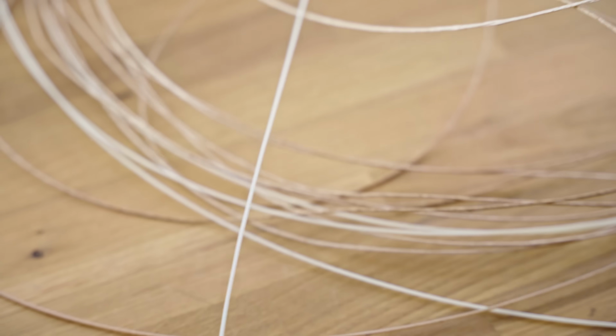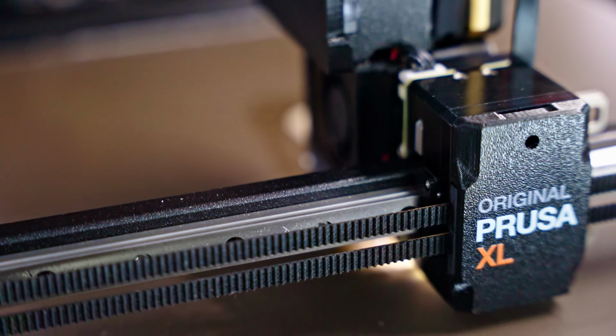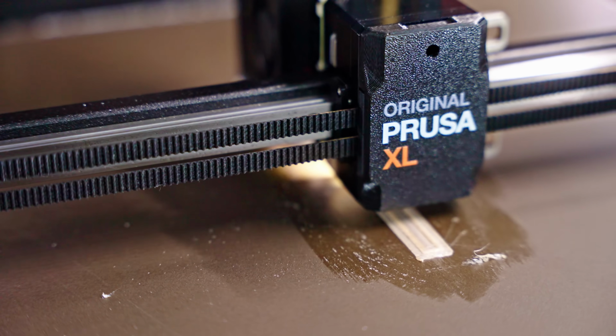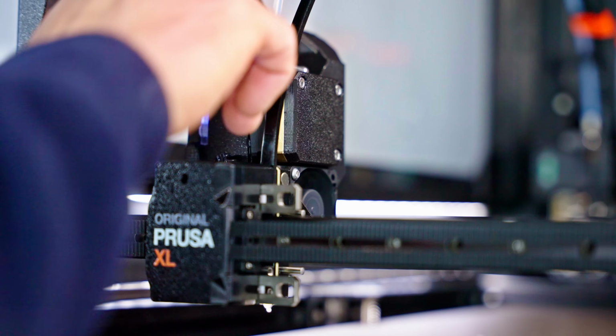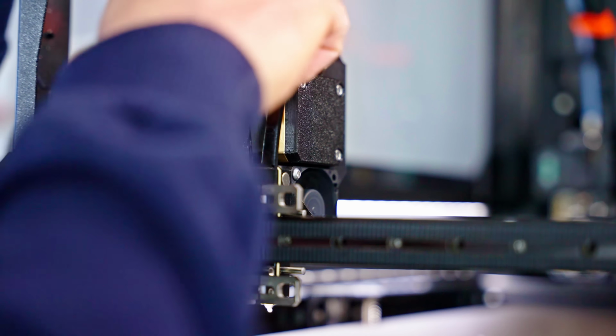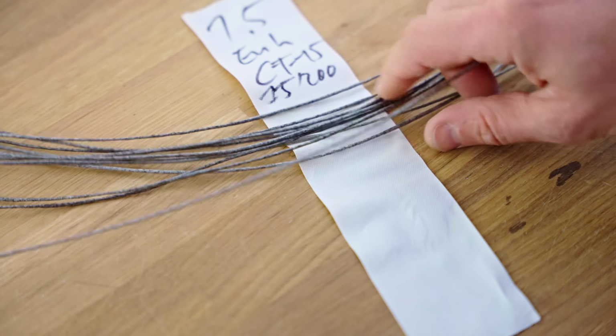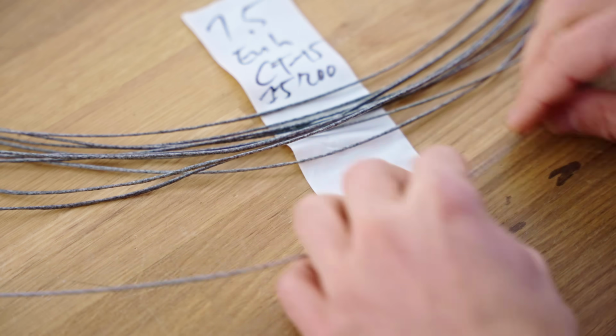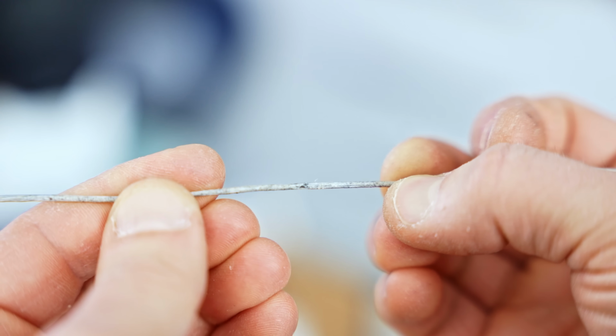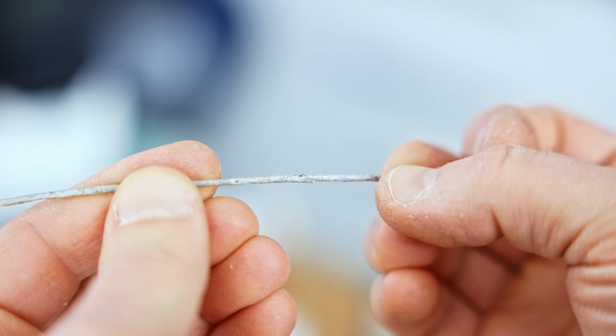The trick with setting the filament extruder to 1.5 instead of 1.75mm worked really well for the plain polycarbonate. But as soon as I tried printing with the materials that had fiber added into them, the extruder was still getting stuck, even though there was no blob in sight. What I found out was that this was because the XL's extruder actually bottoms out at about a millimeter of filament diameter, and the filaments that I made actually all dipped below that at some point or another.